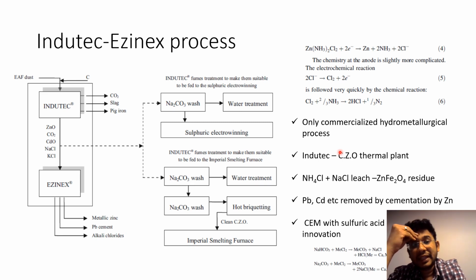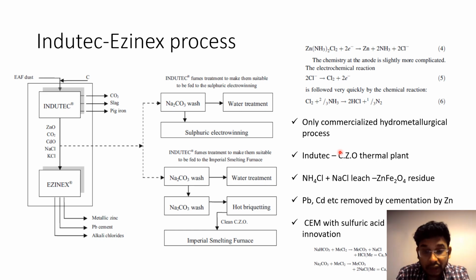So the thing that they were dealing with is that you have the way to do sulfuric acid leaching, right? So that's one way. But it's also possible to do chloride leaching, and it was shown to be quite effective in recovering zinc. But they had an issue there, so they couldn't use it for electrowinning. And I will tell you how they solved it. They solved it by two different ways, and both are very interesting.